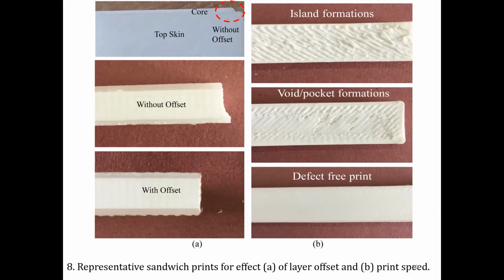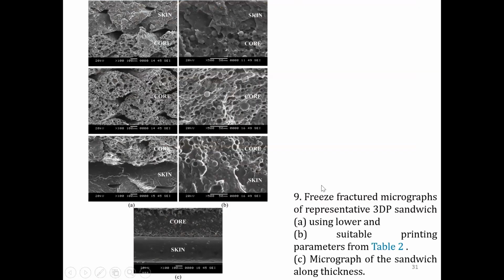If it is not maintained properly, what you see is this, wherein you can see one layer getting additionally deposited, or there is an offset. So with offset, without offset, and these also form some lines, some voids. And finally, you can definitely restore a defect-free print, but make sure that these things are looked into very, very carefully.